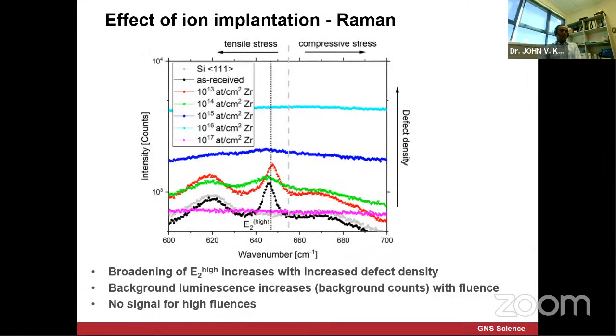Obviously, you do Raman as well. Raman will tell you the broadening, because crystal vibrations are much more sensitive to Raman. If you look at it more closely, this Raman is done with a 514 nm argon laser. You can see that obviously when you do so much doping and implant, you damage the crystals, which is the 10^17 and 10^16 case. But if you do a tiny amount, when you go 10^13, 10^14, you can actually see a shift and broadening, which corresponds to defect density. Obviously, as I said before, when you go to higher fluence, which means you put in too much ion, you damage the crystal lattice. These are all standard information you get from any lab.